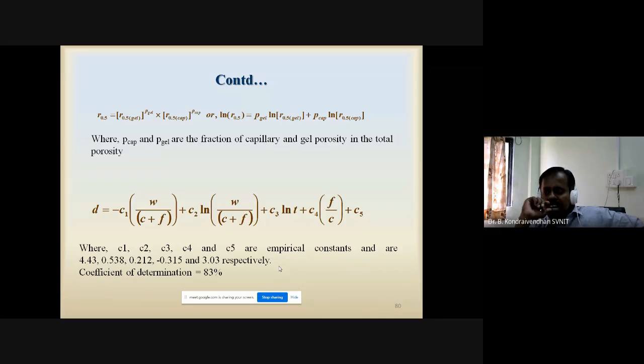That is, R.5 is the weighted geometric mean of R.5 gel into P gel into R.5 cap into P cap. Okay, so you can take the ln on both sides, and you will get the second equation. Here P cap and P gel are the fractions of the capillary and gel porosity to the total porosity.